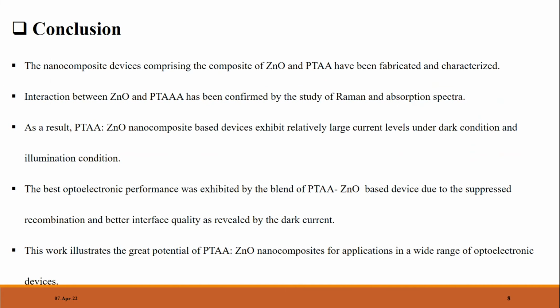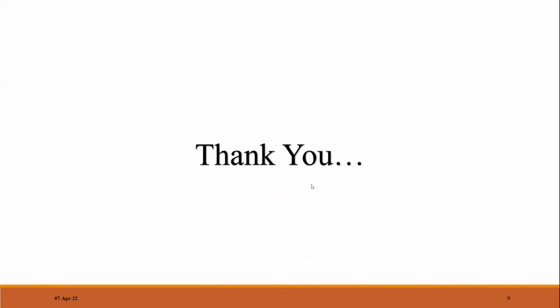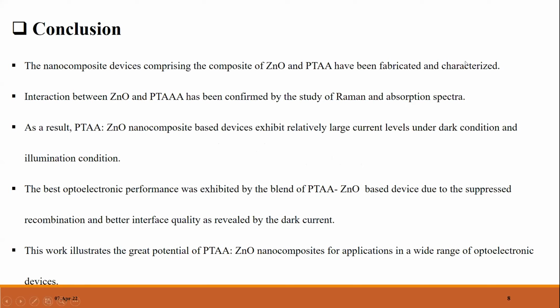The nanocomposite device comprising the composite of ZnO and PTA was fabricated and characterized. The interaction between ZnO and PTA has been confirmed by the study of Raman and UV absorption spectra. As a result, the composite-based device has a relatively large current level under dark and illumination conditions. The best optoelectronic performance was exhibited by the blend or composite of PTA ZnO-based devices, due to the suppressed recombination and better interface quality as revealed by the dark current. This illustrates the great potential of the PTA ZnO nanocomposite for application in a wide range of optoelectronic devices.